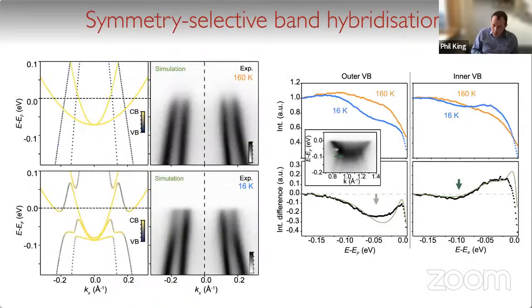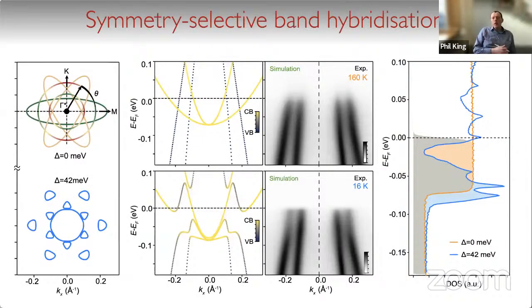And if we include this model quantitatively and compare this to our measured electronic structure, you can see that when we take account of this symmetry-based band hybridization in the system, we can really rather accurately reproduce from our model calculations the measured spectra that we see experimentally. Okay, and so we have then a symmetry-selective band hybridization at the charge density wave transition in titanium telluride. And when you look at the associated density of states from this model calculation, you see that there's really a substantial electronic energy gain that can be understood as ultimately the driving force for the charge density wave transition to happen in monolayer titanium telluride.